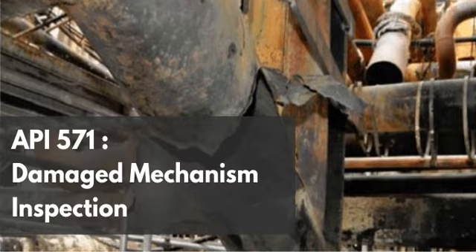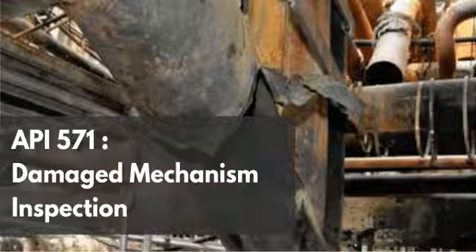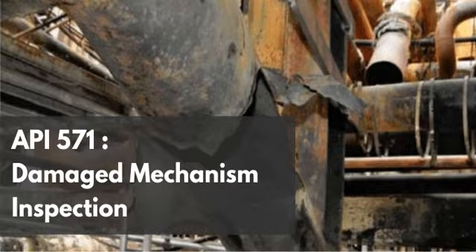But the corrosion doesn't just eat the whole pipe evenly, does it? The engineering guidance gives a massive warning about a specific localized vulnerability in that piping. Yes, the focus narrows even further. The most intense localized damage doesn't happen on the straight runs of that pipe. It explicitly emphasizes that welds are preferentially attacked. Welds. It always comes back to the welds, doesn't it? Yeah. They're always the weakest link.